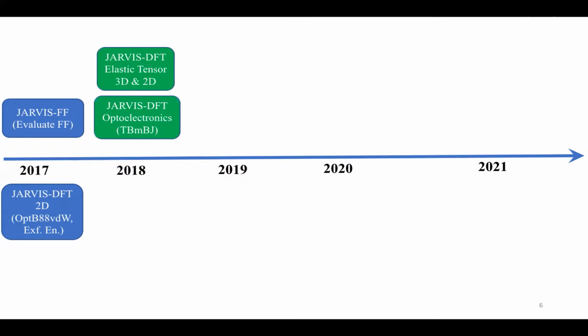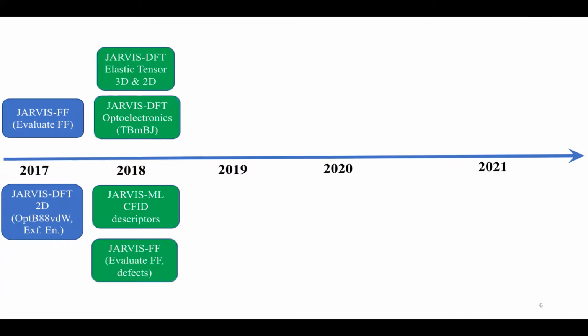And in addition to the band gap database, we also made a database of frequency-dependent dielectric functions. In 2018, we also came up with a descriptor set called the classical force field inspired descriptors, which can describe materials chemistry and structural information. In 2018, we also extended the JARVIS-FF for defect properties such as surfaces and point vacancies. In 2019, we developed the spectroscopic limited maximum efficiency (SLME) solar efficiency dataset.